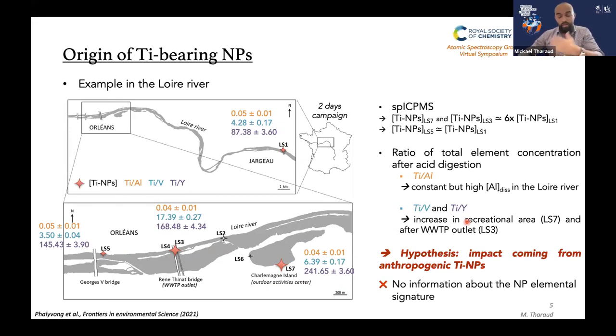However, as I said previously in the previous study, there is no information about the elemental signature of the nanoparticles. And as mentioned by Amy, the fact is that using a sector field ICP-MS, we do not have any information on all the elements at the same time. So that's why we decided to go for a single particle ICP time of flight mass spectrometry. And by applying the single particle mode to that kind of mass spectrometer, we are able to record all the elements simultaneously. And basically, if we have a look here on this signal versus time graph, we can see that we differentiate three different particles. But we also see that we differentiate them based on their composition. Here, for instance, you have a pure gold nanoparticle, while here there is a pure silver nanoparticle. And this one here in the middle is basically composed of both silver and gold at the same time. So this is very interesting.